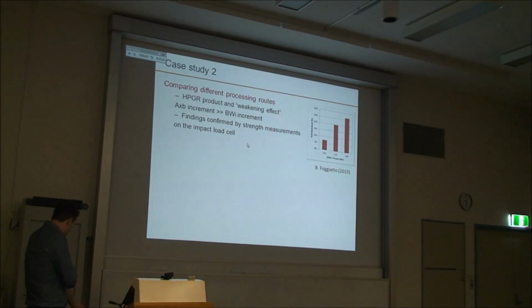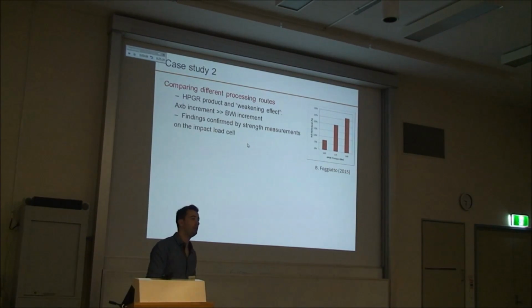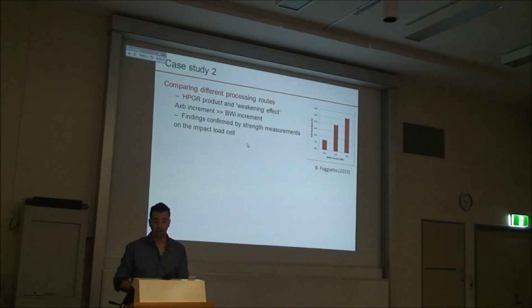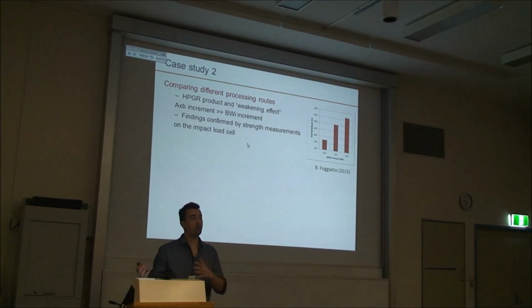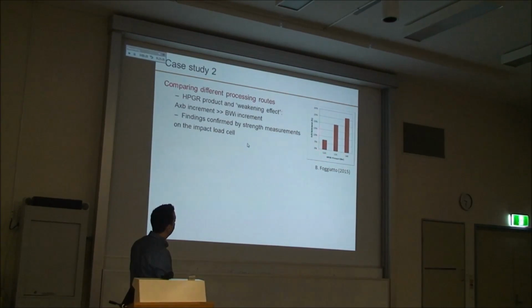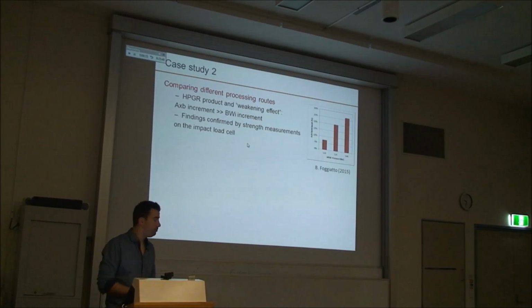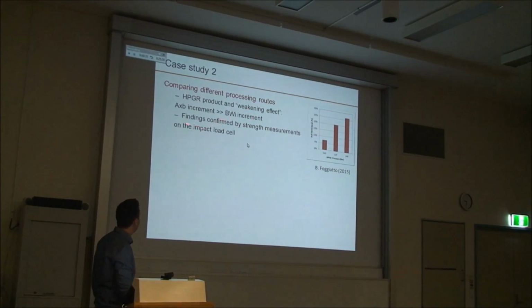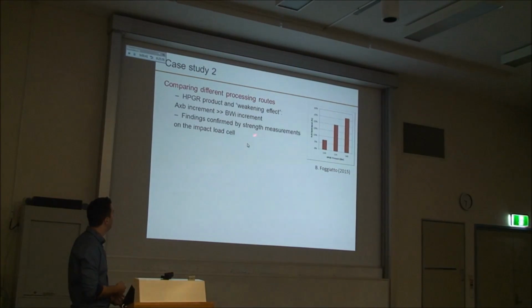Okay. The case study 2 here, we're going to look at the HPGR product weakening. So it's well known that when you put an ore through an HPGR, it's going to be softer. This is the work published by Bianca. Bianca looked at the AB properties of the HPGR product with different pressures. Here the graph shows the increment in AB with the HPGR operating pressure. And she found a significant increase in AB, so a softening of the ore. But she also found out that the bond work index was not increasing significantly compared to the AB. Okay. So basically it was in the order of a few percent, 1 or 2.